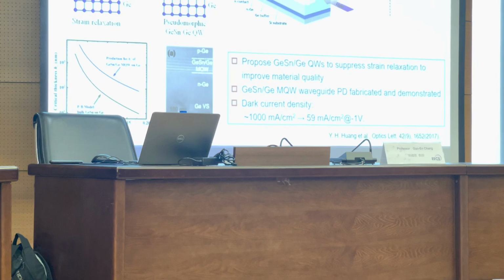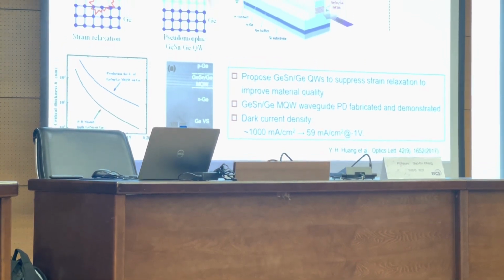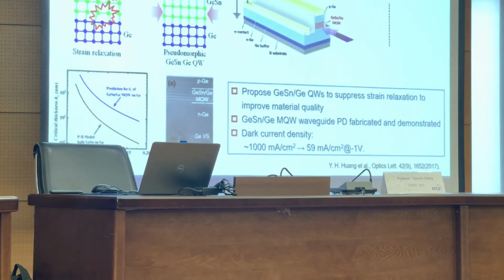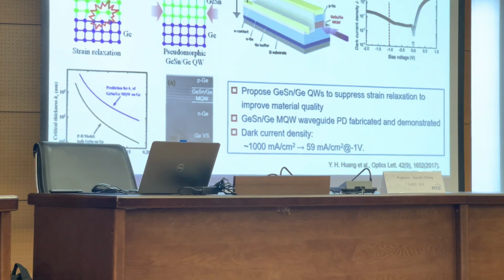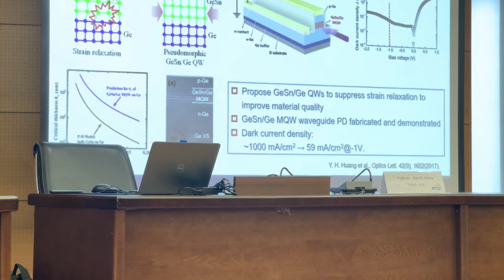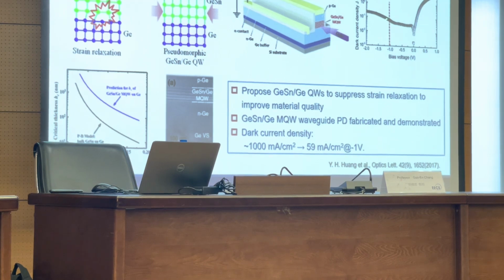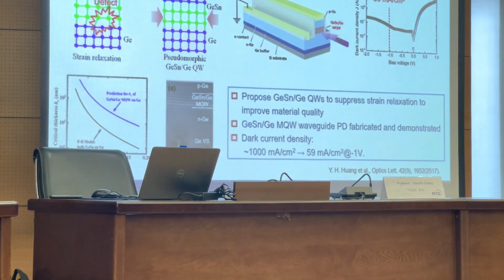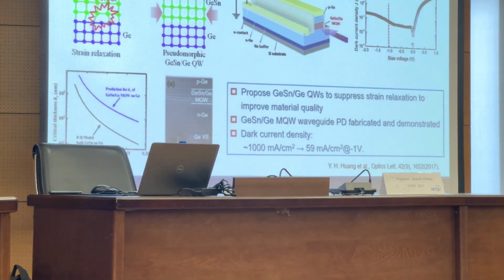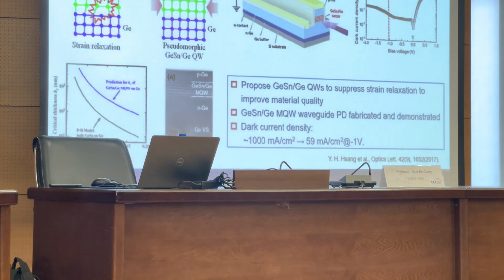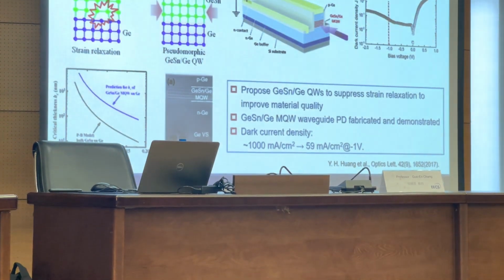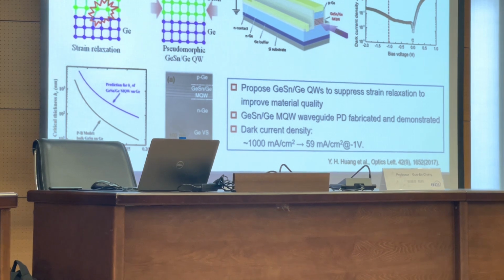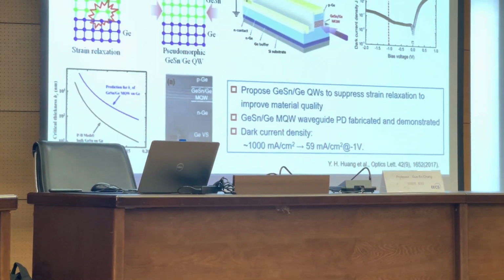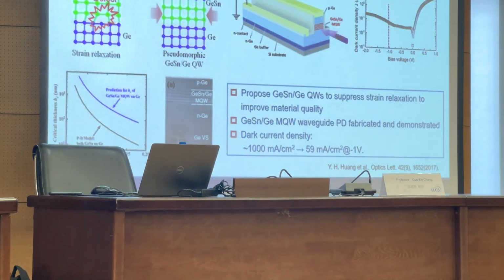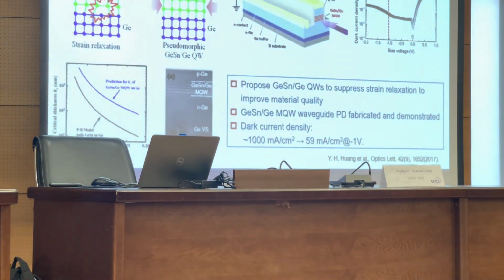Then we grow a germanium tin quantum well structure with 5 pairs of quantum wells, with germanium as the barrier, and make germanium waveguide photodetectors. As we expected, the dark current density at -1 volt is just about 59 milliampere per centimeter squared. This value is almost the best reported in 2017, while the typical value before that was around 1000. So using the quantum well structure, we can suppress the dark current density by a factor of about 20.